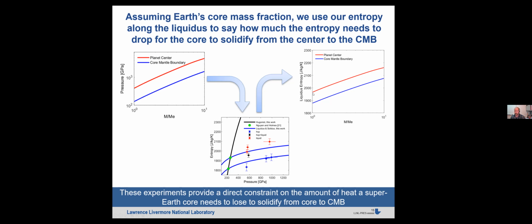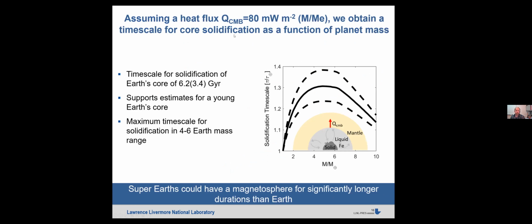Okay, so this is now the liquidus entropy at the planet center and the liquidus entropy at the core mantle boundary. For each given planet size, this tells you the amount of entropy you have to lose to solidify that core, and thus the amount of heat you have to lose. So assuming a heat flux of 80 milliwatts per meter squared, which scales with the planet mass, from Lars Stixrude's paper, we can calculate the time scale for solidification. Just a very simple model.